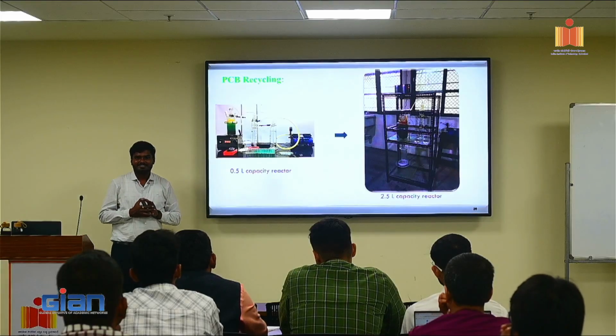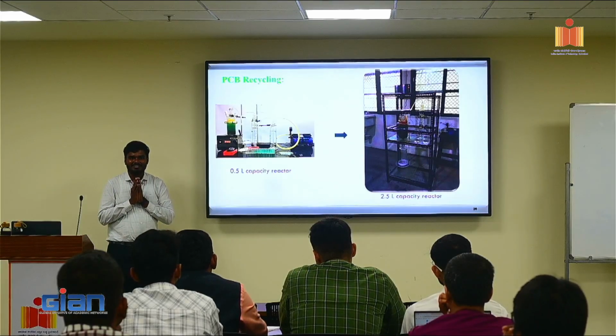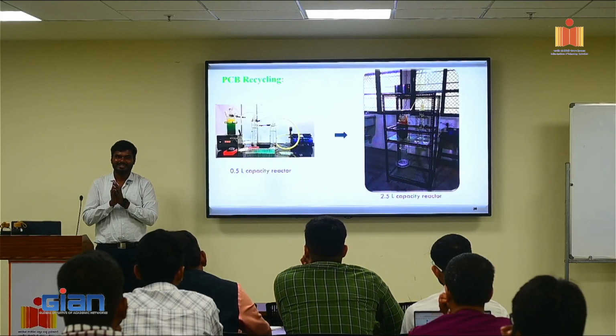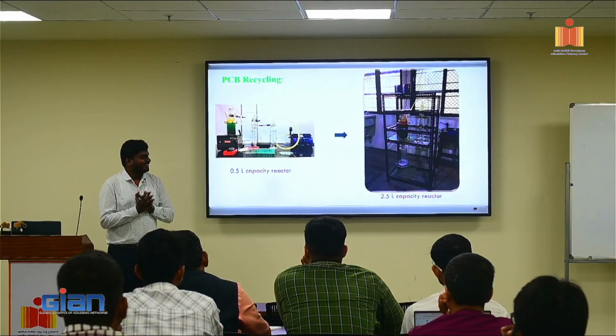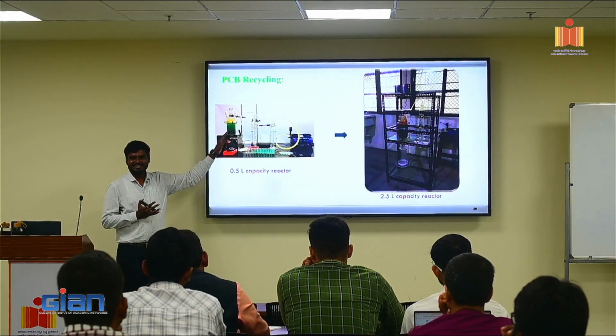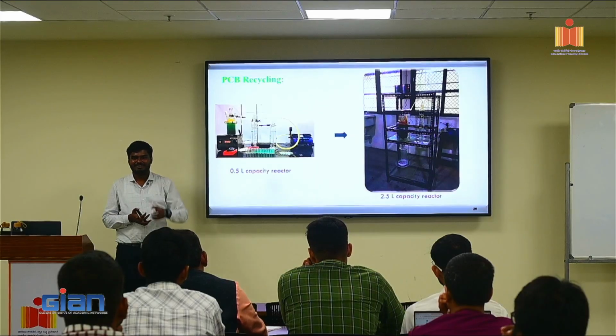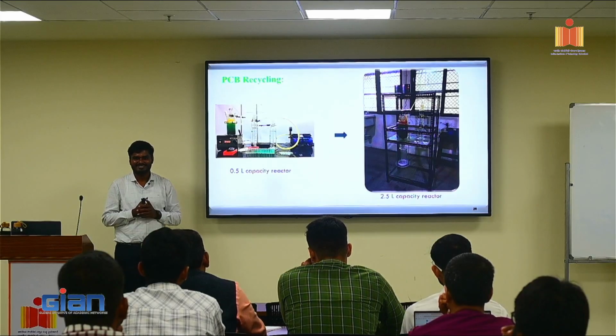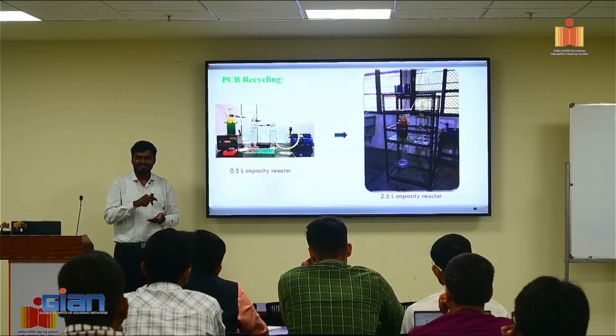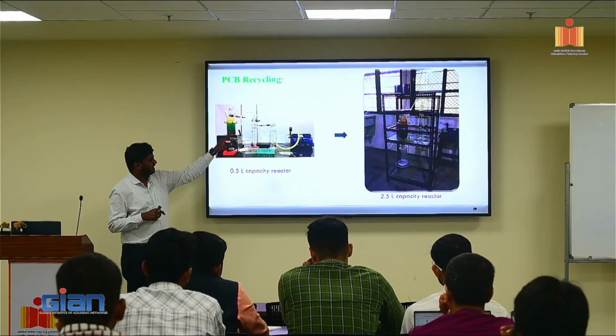Now, one thing is, for my primary dissolution experiment, I have to do it only for 1 hour. If I go beyond 1 hour, other metals will start dissolving. In this, it was easy when I was doing it in the lab. After 1 hour, I take it out, I filter it and separate the solution. That was very easy. When we tried to scale it up, so here this was around 0.5 liters capacity.